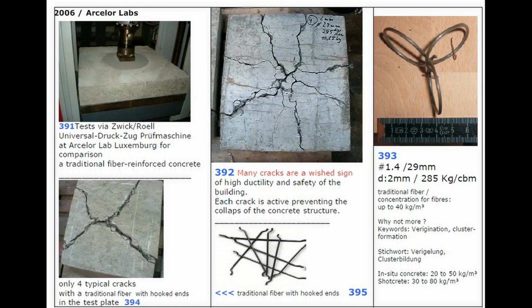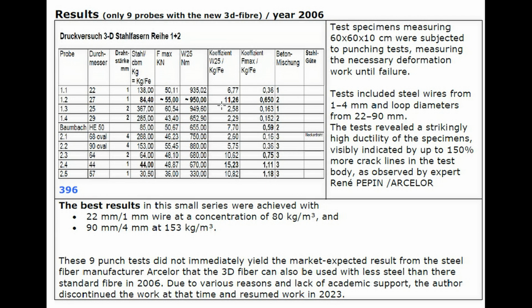and we found a very interesting picture of cracks. Many cracks instead of only 4 cracks with normal steel fibers. And we can count 1, 2, 3, 4, 5, 6, 7, sometimes up to 10 cracks that collect energy. The results can be read here, but it's not the time enough to speak about all.